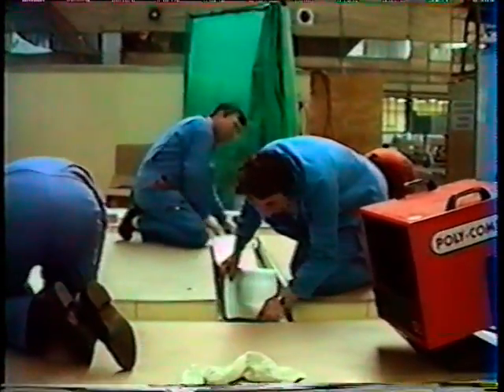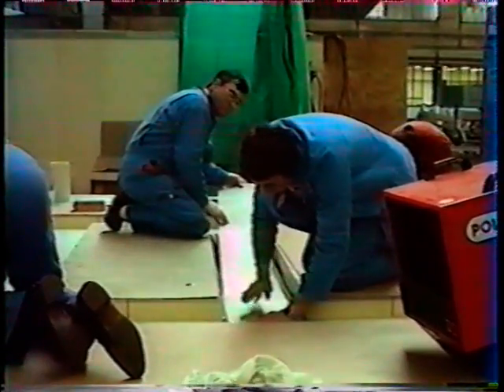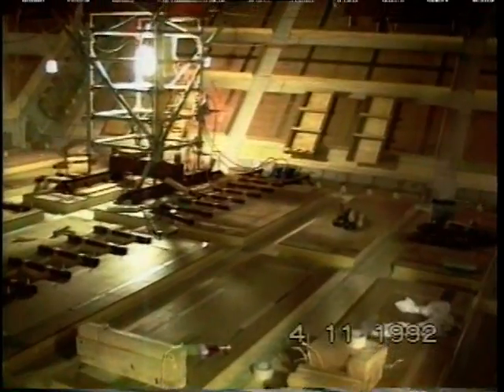For this, a secondary barrier scab is pre-cut and bonded with an even coat of epoxy resin, and then positioned to create the joint between each panel. The bonding process is carried out under a slight pressure of 150 grams per square centimeter, obtained using air sleeves. During this process, the air sleeves are held in place by temporary bars and anchored to the upper plywood inserts of the panels. Following this operation, the secondary barrier is complete over the entire tank surface.